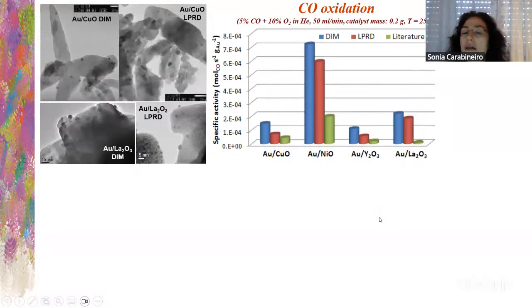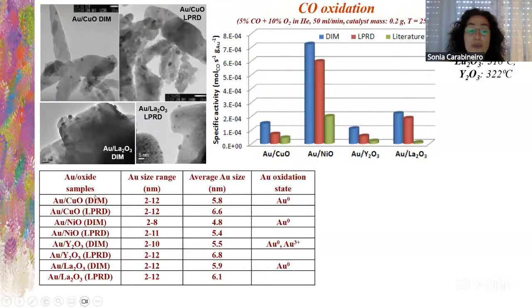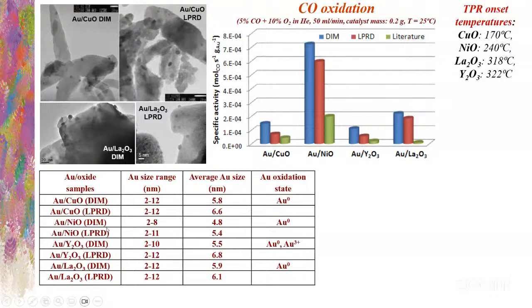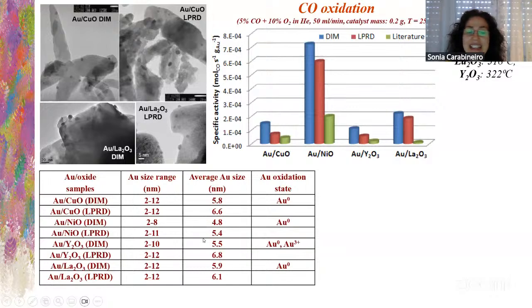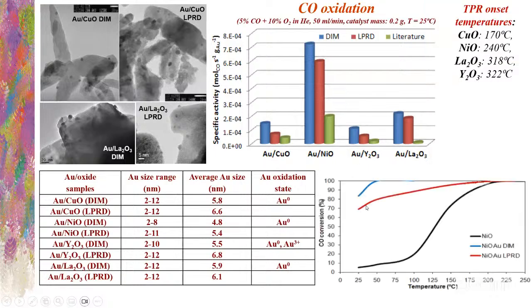So here we have gold on several oxides. We have here copper, nickel, and yttrium and lanthanum oxides. And we see here that the most active is gold on nickel oxide. If we see the onset temperatures, copper oxide should be the most active, which is not, in fact. So if we look here at the size of gold, we see that on nickel oxide it is smaller. The yttrium oxide and the others have gold 0. Here it's gold 3. So on yttrium oxide, maybe it's the gold 3 that is hindering the catalytic activity.